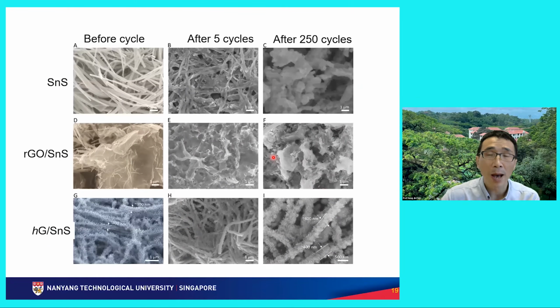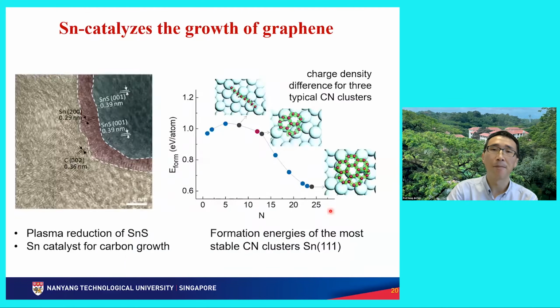And we also look at what happens after many cycles. If you look at pure tin sulfide, the nanowires break into particle powders after just 5 cycles. If you look at a mixture with RGO, this is tin sulfide, this is RGO, you also don't see the original feature anymore. But this one, even after 250 cycles, you can still see the distinct features, right? All the nanowires inside probably become polycrystalline, no longer single crystalline. But anyway, the individual wires are still there. We will not go into details of why it can grow, it is because of a self-catalyst growth.